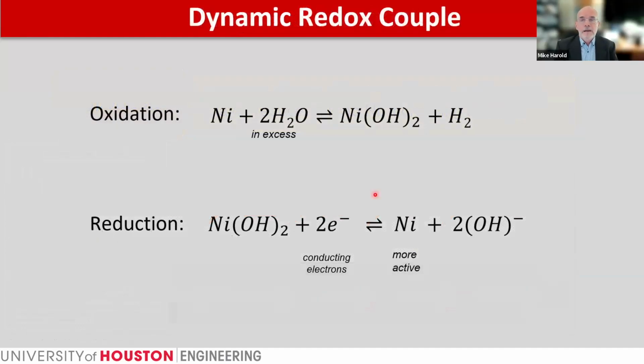So we essentially have a dynamic redox couple, we believe, in the top layer that involves directly electrical current. The reduction, which I'm reproducing here, could be represented by nickel hydroxide being reduced to nickel metal, producing hydroxide anions, which then can undergo further reaction. That is balanced by oxidation by the gas phase. We have, as you know, I said a 3-to-4 ratio of steam to methane. So we have plenty of water that can serve as a soft oxidant of the nickel, producing nickel hydroxide and hydrogen.